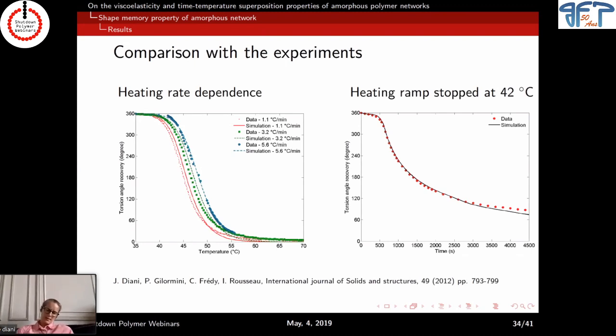So basically, what we just proved is something that probably a lot of people from the physics of polymers would say is obvious: that the shape memory property of amorphous polymer networks is basic. It's a signature of intrinsic properties of this material, which are the viscoelasticity and the time temperature superposition, and that's nothing else. It's one thing to understand it. It's another thing to prove it, and to be able to give constitutive equations that would help predict the behavior of this material.